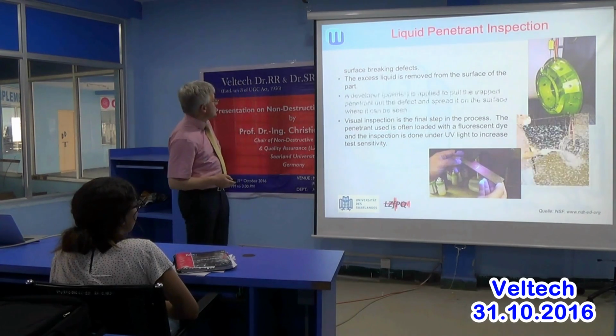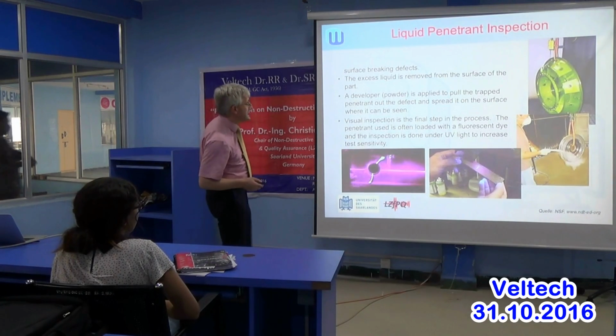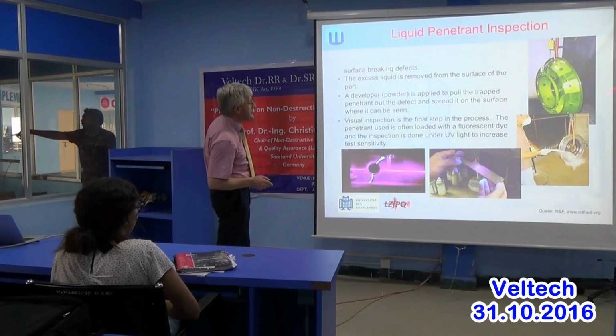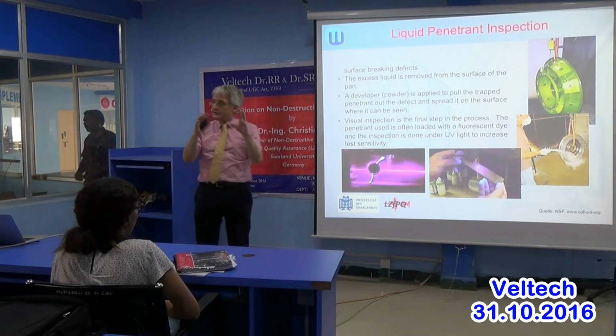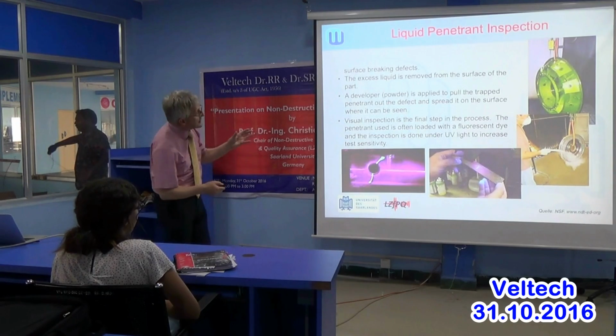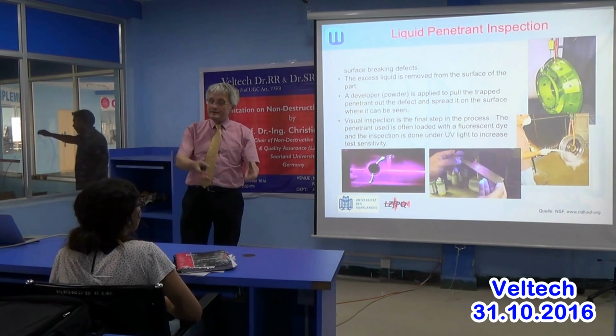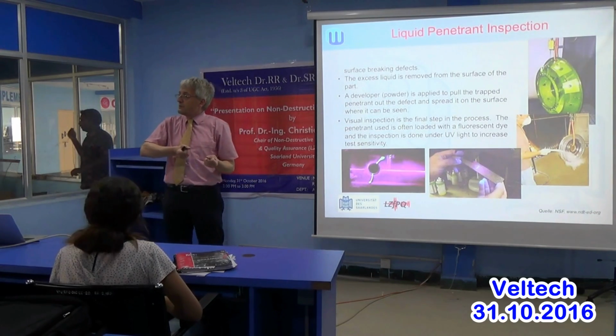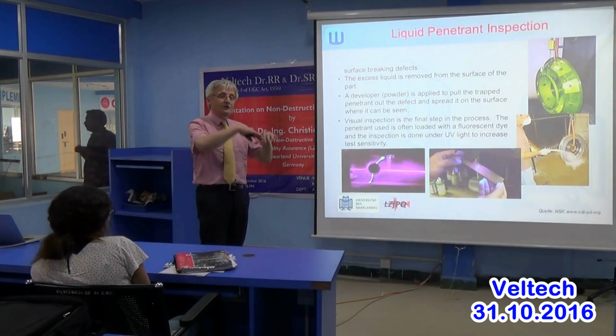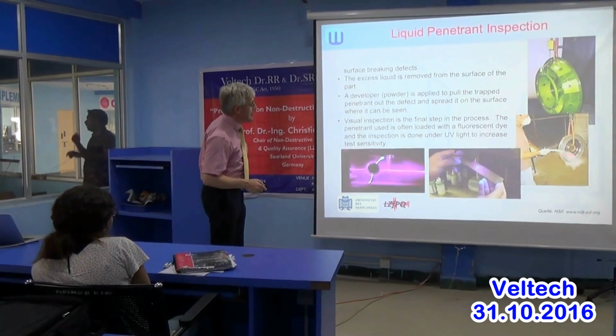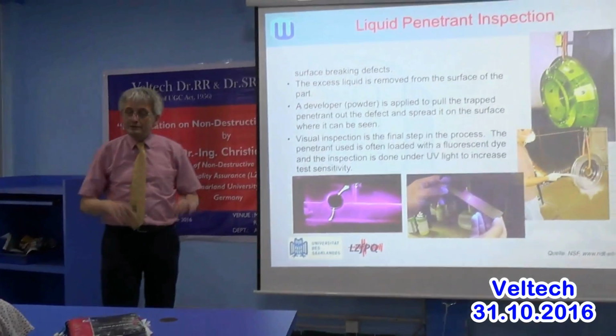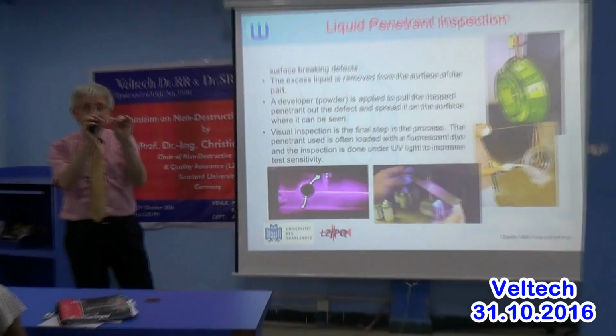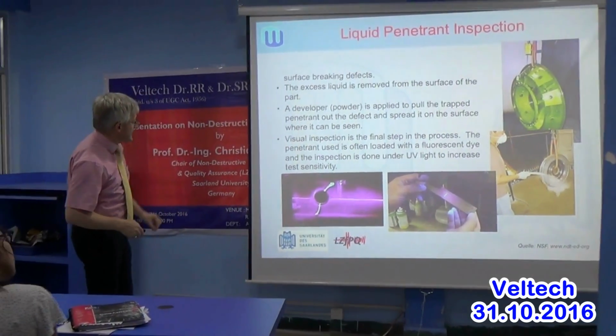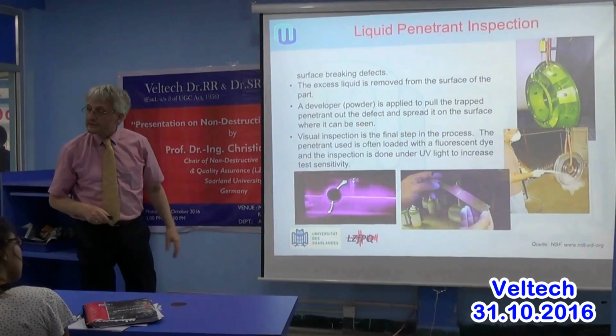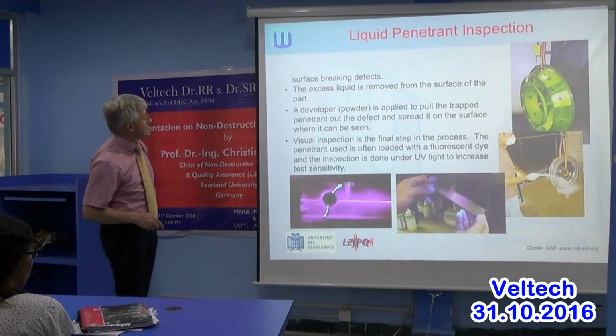of the component. I may not mix some of the sequences exactly right here, but after we take off the liquid, we spray it with a powder, which is basically a developer. If the liquid is, for example, green, or maybe even red, then the developer will pour out the remaining red liquid from the cracks. Then we will see on that white powdered component very small red lines, and we'll see, okay, this is where cracks are. We can even amplify that with some ultraviolet lighting, and then you definitely see cracks and imperfections. So this is what the liquid penetrant inspection does.